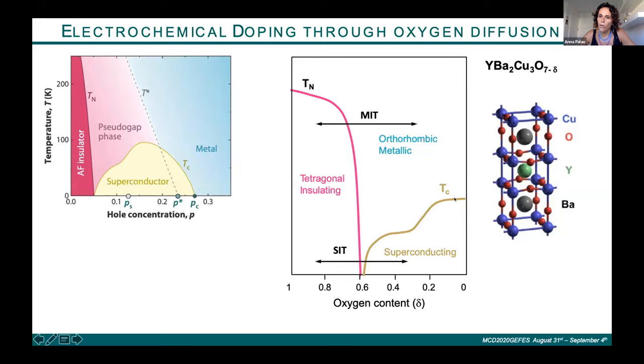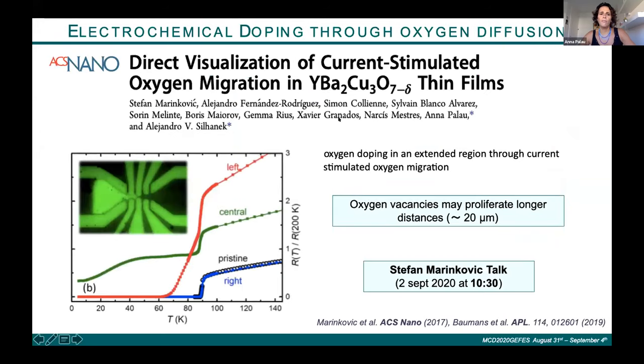At zero or very close to zero, we have the system close to O7, which is the orthorhombic metallic and superconducting phase. And when we reduce the oxygen content by increasing this delta, so we go close to O6 here, we induce this transition from the orthorhombic to the tetragonal phase, which is insulating. So this transition also can be induced at low temperature, going from the superconducting to the tetragonal insulating phase, or above TC, going from the metallic to the insulating phase.